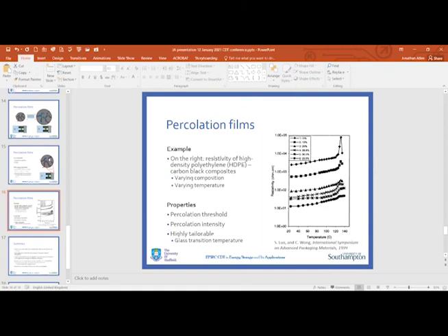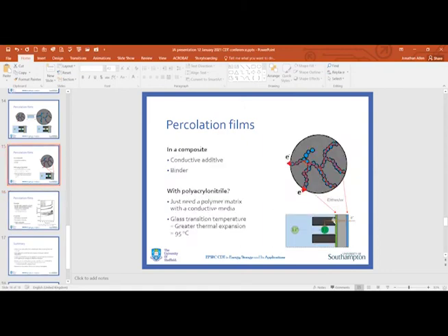Yes. If I go back to here, the material that will be doing the percolation effect is this small little strip. You've got the cathode or anode material on top, and this is your aluminium or copper current collector. So this small strip needs to be electronically conductive. Otherwise, it won't work during normal operation anyway. So it's about trying to balance getting a good conductivity, so that you're not hindering the operation of the cell, against getting a good shutdown effect. It's a bit finicky, and it's something I'm going to be looking at quite extensively. Yeah, it's something to consider. Thanks for that.